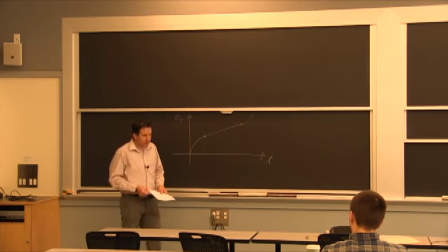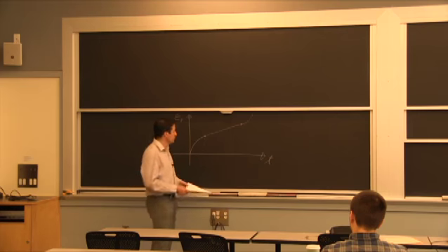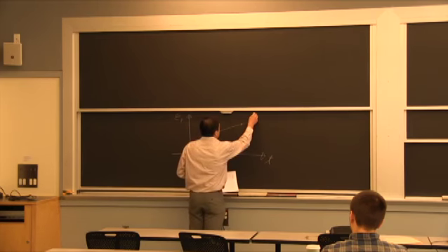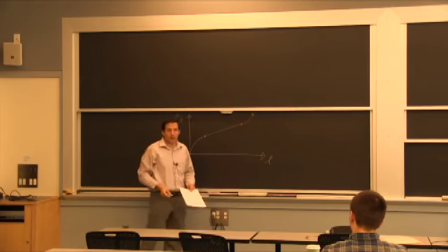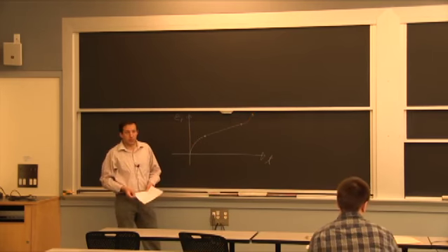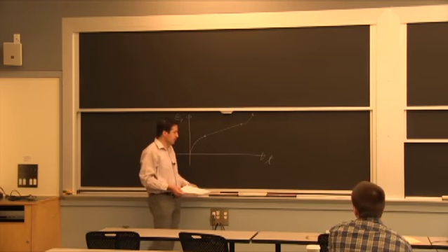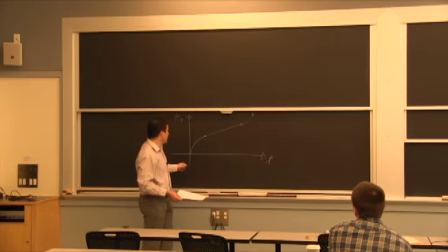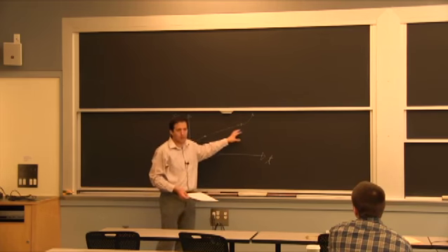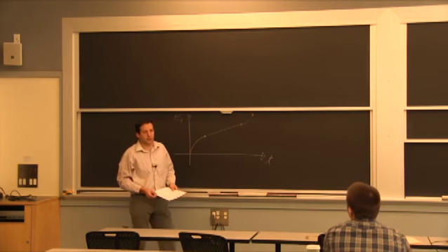If we go back to our lecture on steel, we talked about fracture toughness. So when you reach this condition here, typically you have a crack, and it's at a length that meets the overload condition. And that stress intensity factor is not too much dependent on the overall history. You can essentially use your stress intensity factor.